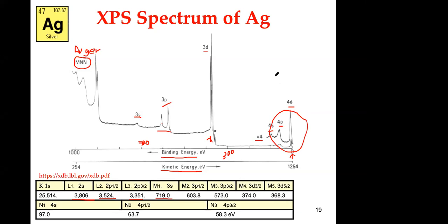binding energy, usually they use UPS, ultraviolet photoelectron spectroscopy, to characterize this better. And you get a lot of information for molecules, for example, on the bondings of the molecule. And I'll show you some spectra of polymers. And for polymers, they use this area as a fingerprint to identify polymers. So this is close to the valence band. So again, everything is there, this quantized structure and levels, and that's the values that you see.